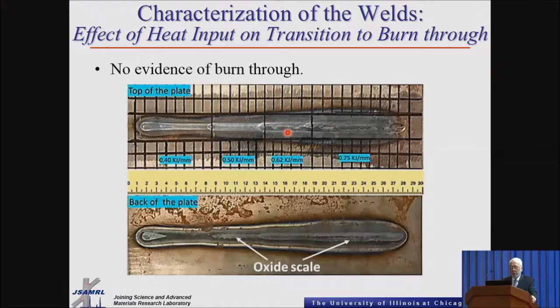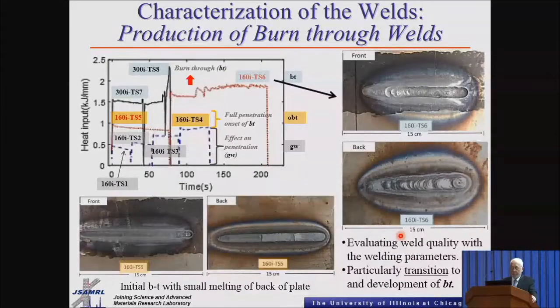You can see that when changing the heat input, the mass of weld being produced increases. On the back side of the plate, again, you don't have any burn through, so you don't have any excess weld metal coming out. Okay, but now if we decided to take a look and compare the changes in the heat input, trying to classify the type of weld that we have.